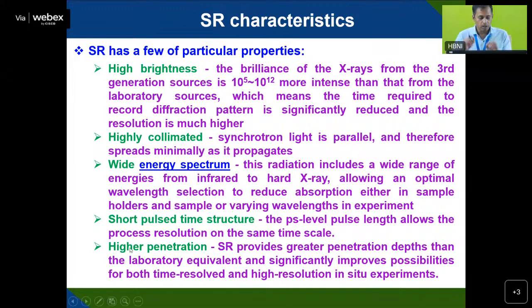You also have a short pulse time structure. Picosecond level pulse length gives you time resolution for processes. It is high intensity and high brightness, which means the penetration depth is greater than in laboratory conventional XRD. That improves the possibility of both time-resolved and high-resolution in situ experiments being done here.